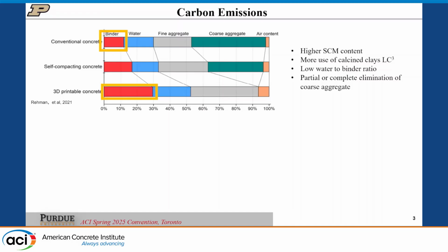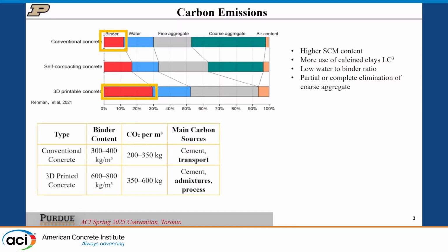We're also putting a lot more admixtures into our systems, and even though sometimes these admixtures are at low content, they have a much higher carbon footprint. If we look at the carbon emissions of conventional concrete compared to 3D printed concrete, even if we replace half the cement with supplementary cementitious materials, we're typically around the highest limit we'd see with conventional concrete in terms of carbon footprint. Conventional concrete has a carbon footprint between 200 to 350 kilograms of CO2 equivalent per cubic meter, and 3D printed concrete right now, with a lot of the literature, is between 350 to 600 kilograms of CO2 equivalent per cubic meter.